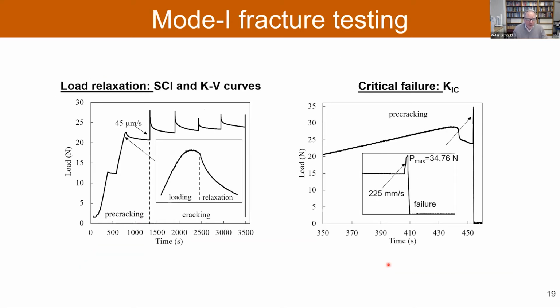And there are two types of measurements being done. One, let me look first at the right diagram here, is we just load it until the fracture fails. There needs to be a seed fracture there, so it needs to be notched, and that's called pre-cracking. Then we load it at a fairly rapid rate and measure the stress when the sample fails. That is called the fracture toughness, which is intrinsic to the material, so it's characteristic of the material.